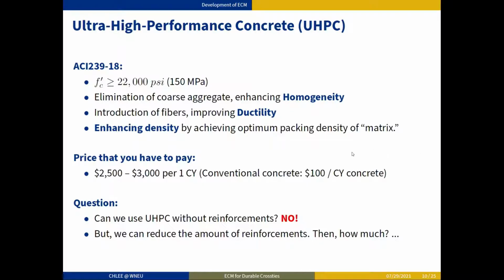However, the price that you have to pay for using UHPC is $2,500 to $3,000 per cubic yard, as compared to conventional concrete, which is $100 per cubic yard. It is quite expensive. Then the question that we had was, can we use UHPC without reinforcements? Because if you use fibers in the UHPC, then that also provides some of the tensile strength.